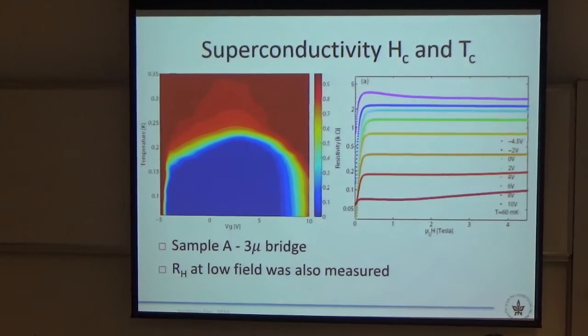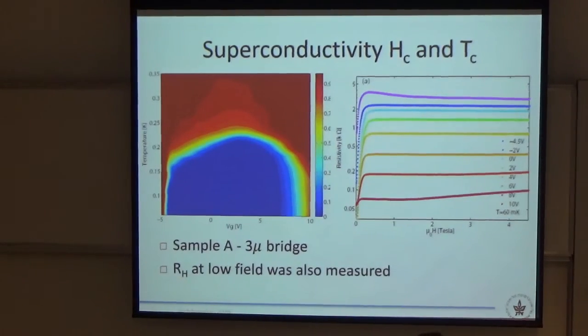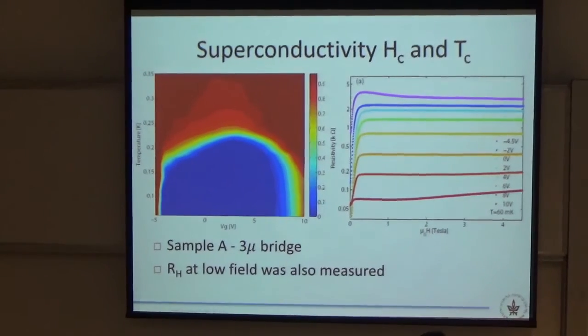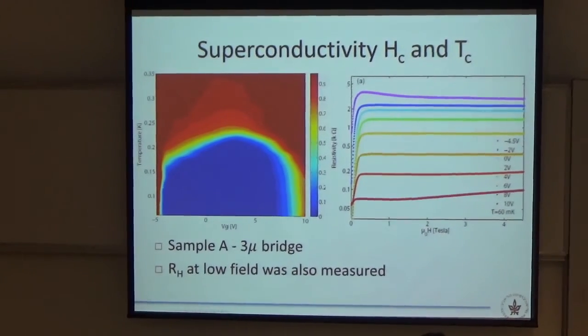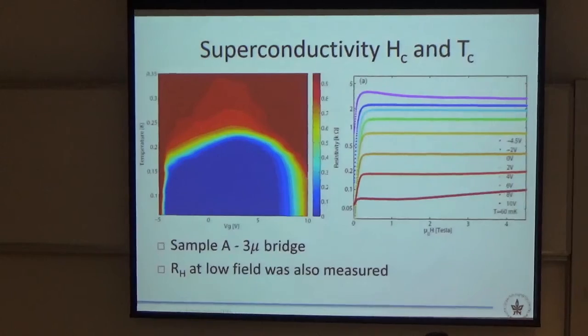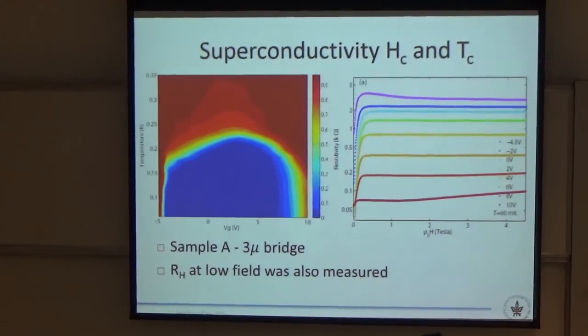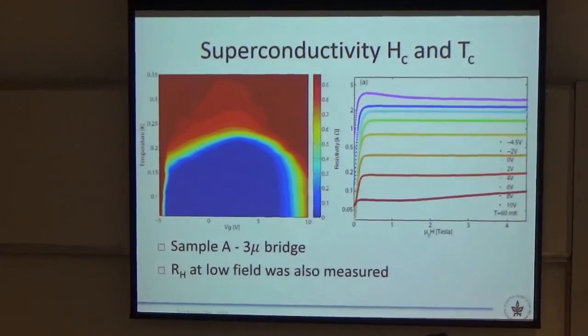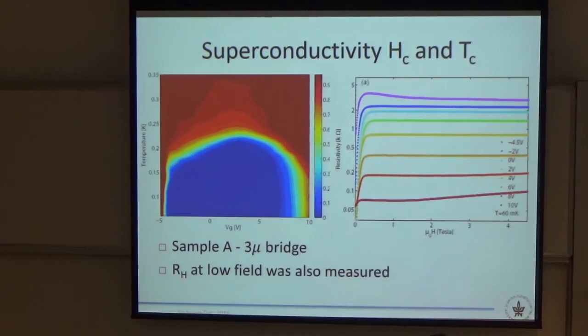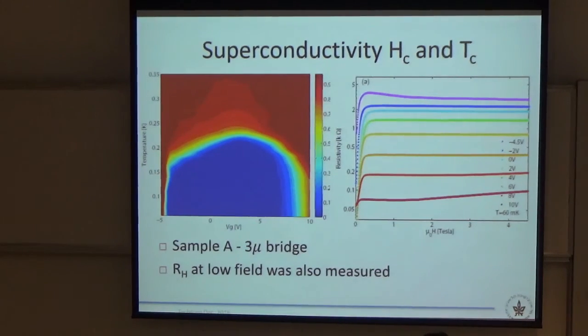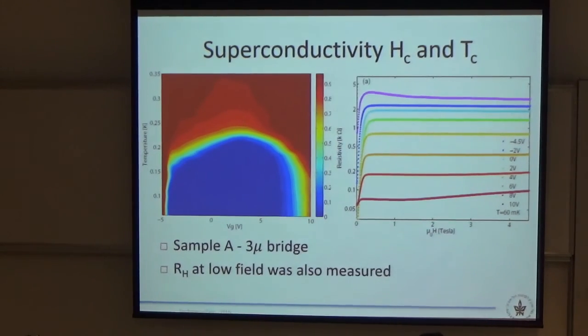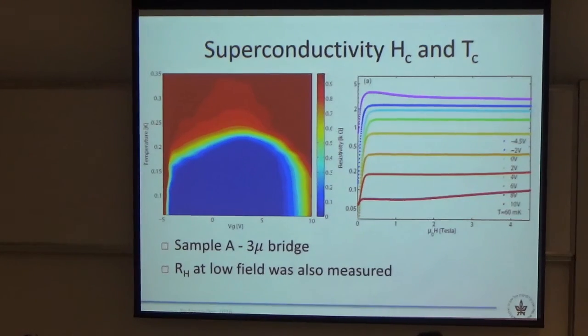Here it's very dilute. The system is 10 to the 16 per centimeter cube, or 10 to the 12, 10 to the 13 per centimeter square. So it's a very dilute system. This is why it is so. And also the dielectric constant is gigantic. With the cuprate, if you apply gate voltage from strontium titanate, maybe you change Tc by half a Kelvin, if you're really lucky, and you have something really, really thin. Unless you are Hendrik Schon.